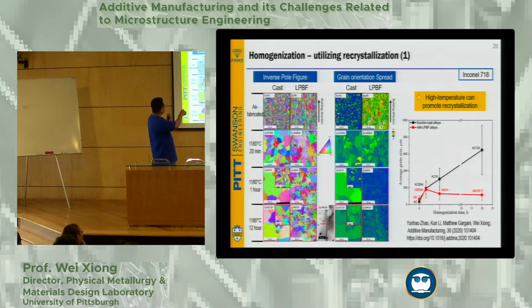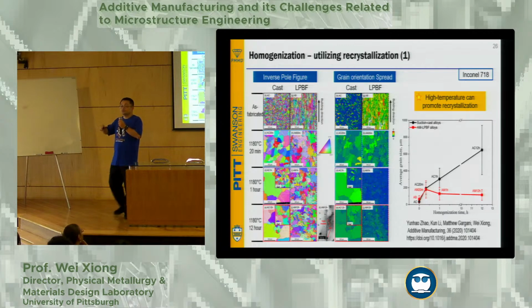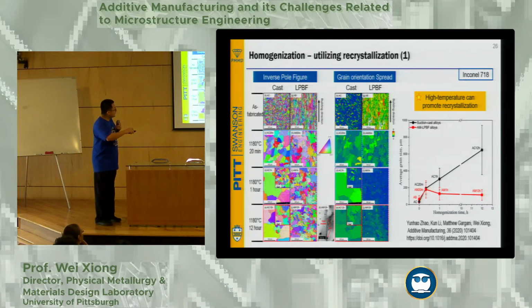And then if you dissipate the stress at high temperature, as you can see, this stress helps you refine the grains during the recrystallization process. And if you do an analysis with grain size, the additive manufacturing grains actually become even smaller than the original one here, all right? That's a good indication. That means additive manufacturing doesn't always bring trouble if you can really define the post-heat treatment well, okay? That's encouraging.